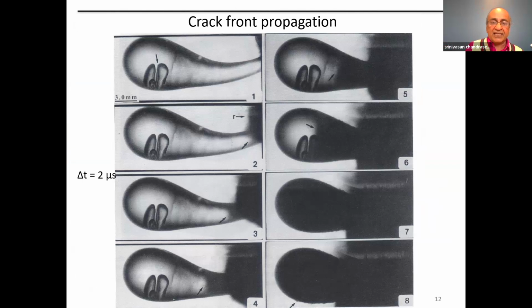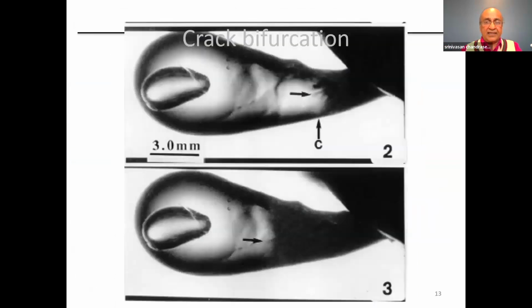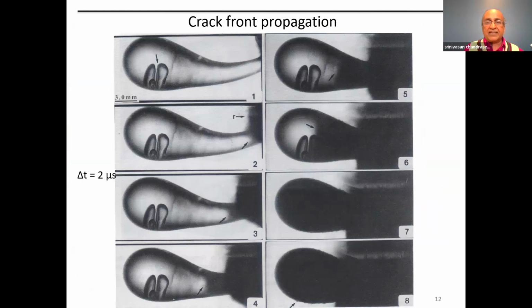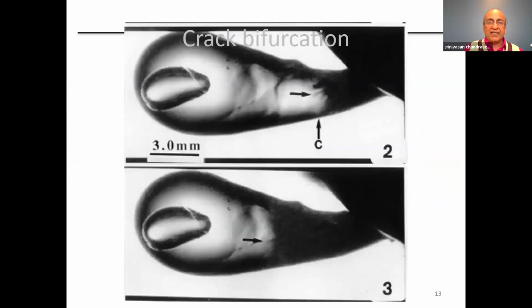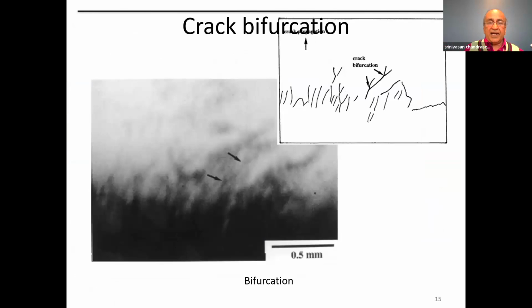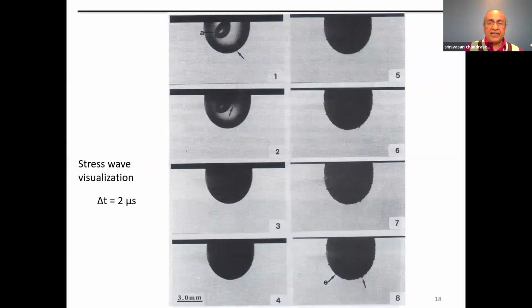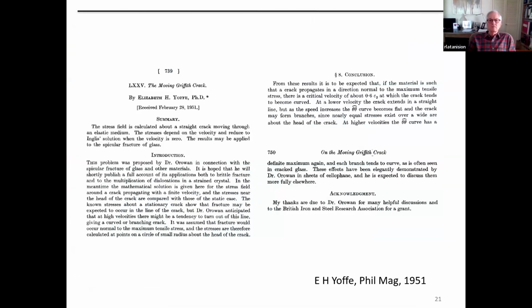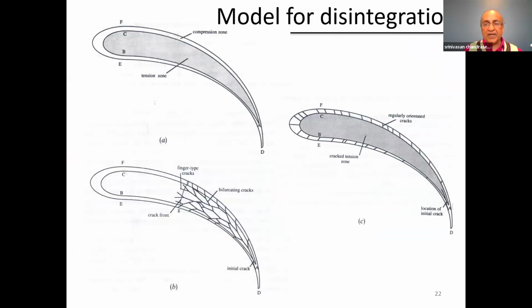So the bifurcation events are seen ahead at the crack front. We got the crack velocities from pictures such as this, and eventually this bifurcation repeats ad infinitum, and the core of the drop is completely filled with fragments. Usually, when the crack enters the compression zone on the surface, the cracks will slow down because now there's no tensile field.